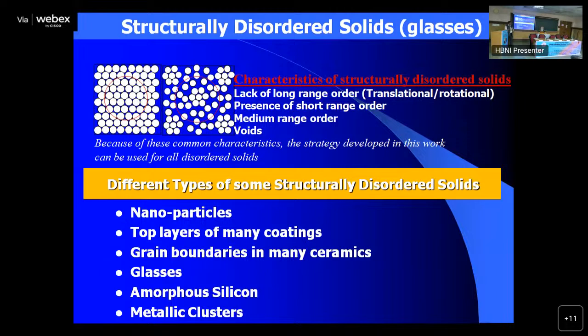That is, let us say, glass. Glass structure has disorder, that's what they say. But actually, if you look at the structure of the glass, it doesn't have long-range periodicity like in a crystalline material, but you have short-range order. That is very well known. It is known for metallic glass, and is also known for non-metallic glass. And many other materials which are not crystalline also have short-range order. By the way, that group is much, much larger than the crystalline material group. Crystalline material is a very small group.